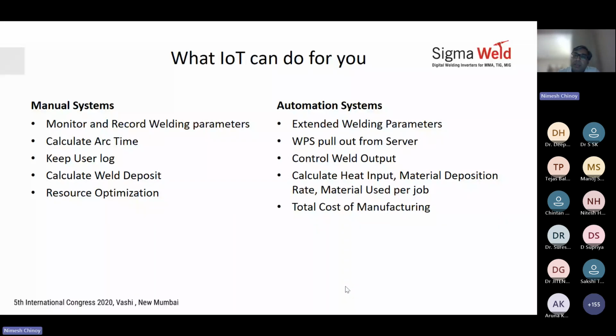Right? If the system was automated, that means the system was working on an SPM or a robotic system, you can have extended welding parameters, which would mean the movements of the torch or the job, rotation speed, travel speed, all this data you could capture if it was an automated system. How do you capture that? You capture it through the motor, you use an encoder or something to give you the data from there, or you could get the data directly from the PLC. Then the welding procedure that the welder supervisor has set and put onto the server could be pulled out directly from the server and fed to the automation system.